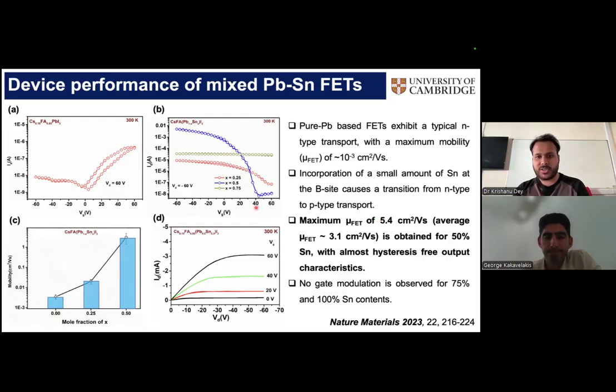And then we tried to go to even higher tin content. So this is for 50-50 lead tin. If we go to higher tin, we can see that the transfer characteristics look flat. That means the current is not changing with the gate voltage, and this happens when the channel is already full of charge carriers, or when the channel is very much doped. So it acts like a semi-metallic semiconductor, which is not really good for a transistor, which is why you don't see any gate modulation of the current.